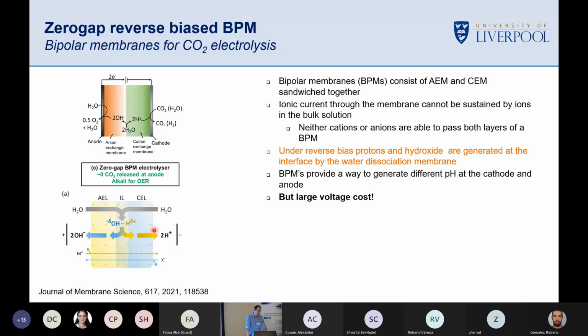And the good news is we can then have an anode which is operating at high pH, and we know that for water oxidation, of course, we've got a limited selection, really a selection of one. I would argue for water oxidation catalysts at low pH, which would be iridium oxide. Here we've got the world to choose from. Lots of different things. We could put just a nickel mesh in if we wanted it to work particularly well.